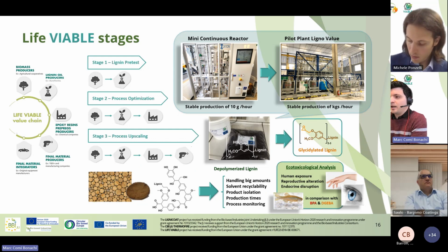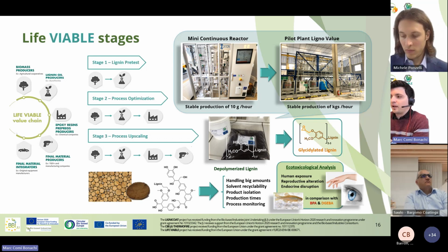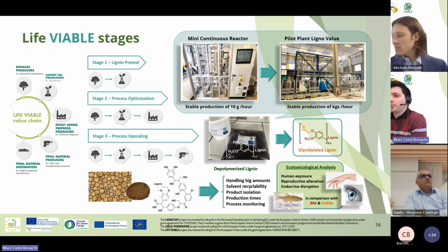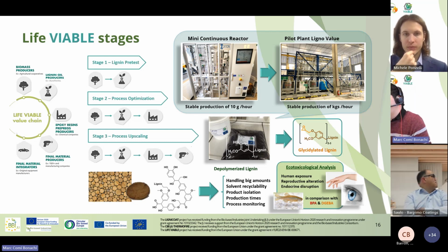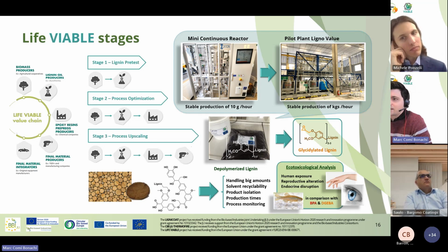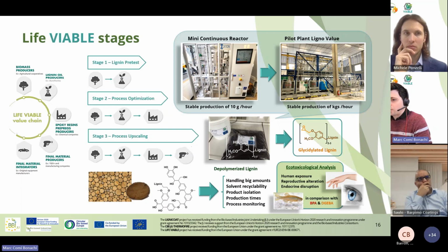Then we also did tests on the reproductive alteration of the zebrafish, the fish that you see here. We put these fish in different environments, one with bisphenol A and one with a little bit of our lignin, under the same conditions, and we saw that we did not alter the reproductive cycle of the zebrafish as much with lignin as with bisphenol A, which is really good news also. And finally, the endocrine disruptor. We measured the activity of these receptors, and we saw that lignin activity is 100 times, two orders of magnitude, lower than bisphenol A, which is also really good news. All of the results will be published in the literature. We are planning to publish in the next month.